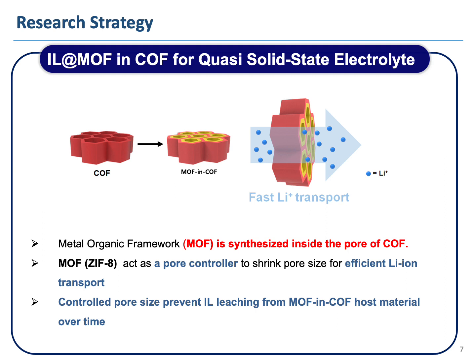This ionic liquid laden COF with pore controlling MOF, in which ZIF-8 is chosen as the MOF, acts as a pore controller to shrink the pore size for efficient lithium ion transport. The ZIF-8 synthesized inside the pore of COF controls the pore size to prevent leaching of ionic liquid from the COF host material over time. At the same time, it will increase the ionic conductivity and the lithium ion transference number of this composite electrolyte for the application of battery.